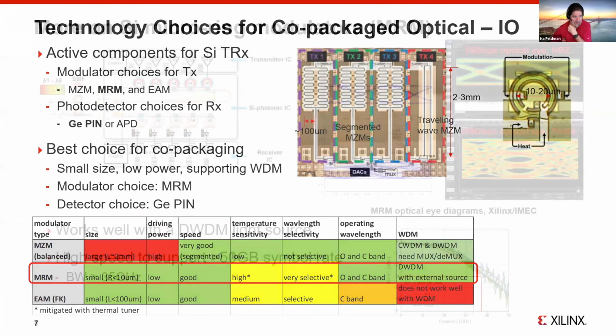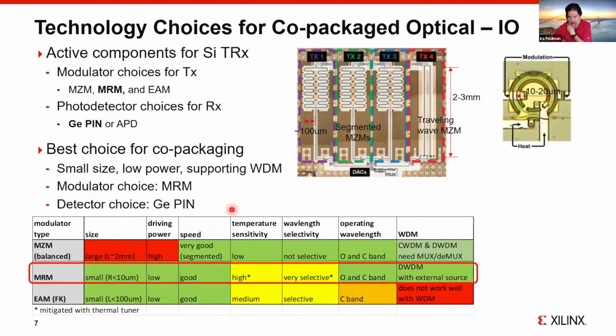On the modulators, there was a question: is there a huge power difference between the MZM and the MRM? Are there any relative figures of merit? Yes, there is a very significant difference between them. One way to think about it is a segmented MZM. Say you have a 2 millimeter long modulator, and for 50 gigabit per second operation, you probably need to divide it into about 10 segments in order to treat each segment as a lumped device.